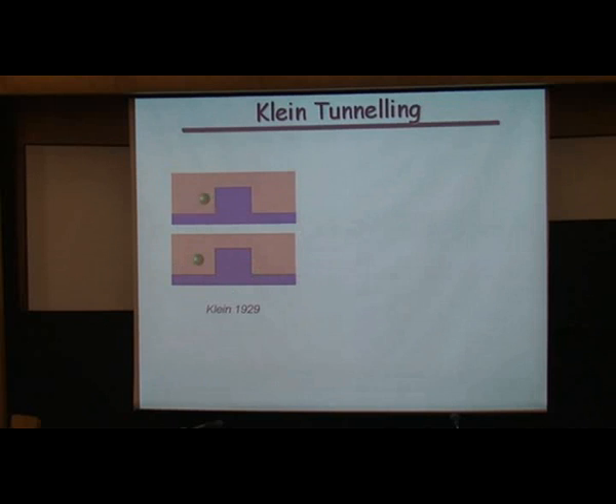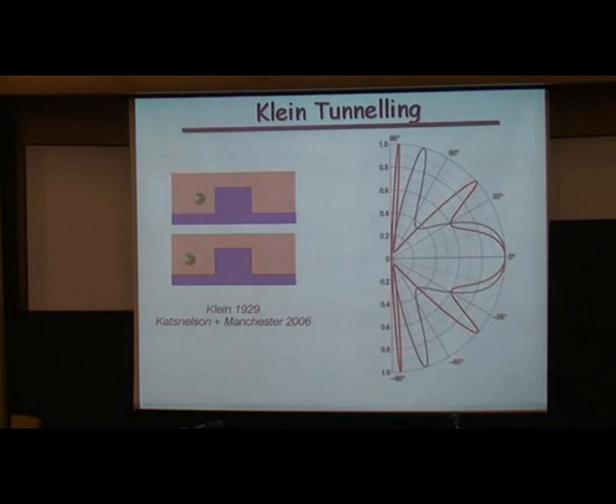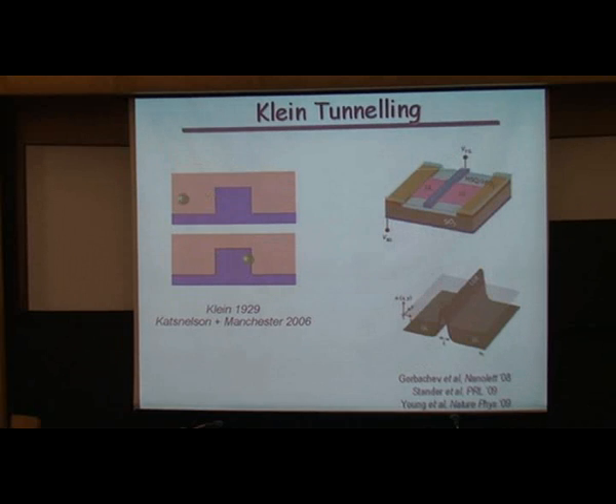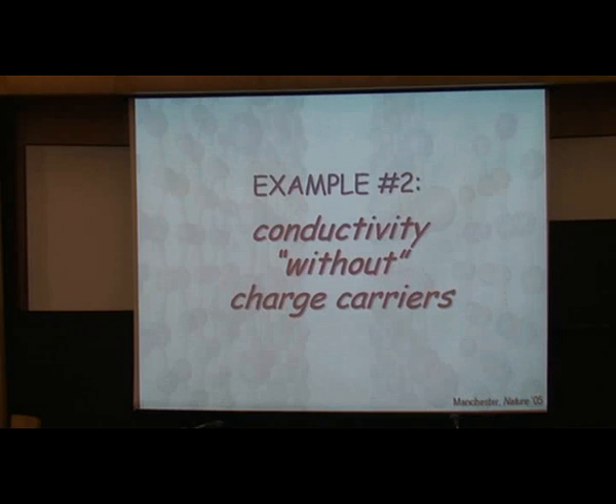ultra-relativistic particles, a consequence of the Dirac equation is that whatever barrier you construct, you can't localize your particle. It moves through the barrier with 100% probability, first found by Oscar Klein as a consequence of the Dirac equation. So we expanded a little bit the same formulas for the case of our particles a couple of years after we started doing graphene, and in the last 2 years there are plenty of experimental observations of this Klein tunneling in material, and it's a very important phenomenon. Many properties of graphene, like why you can't localize particles, why it's so difficult, why you can't make a barrier, are based on this Klein tunneling phenomenon.